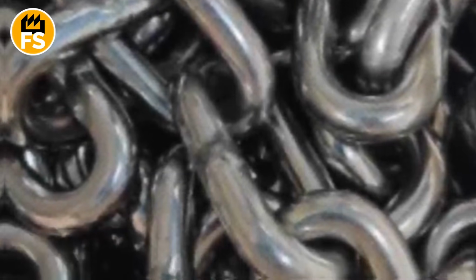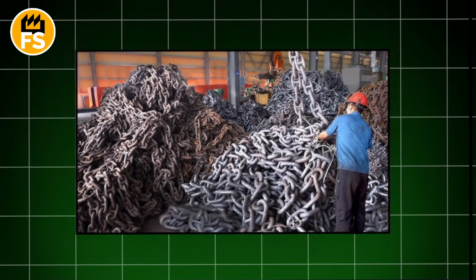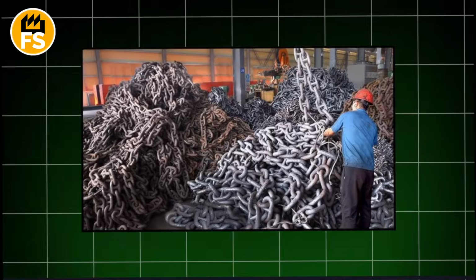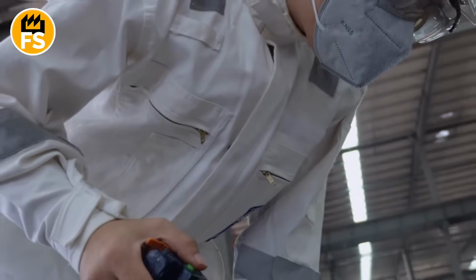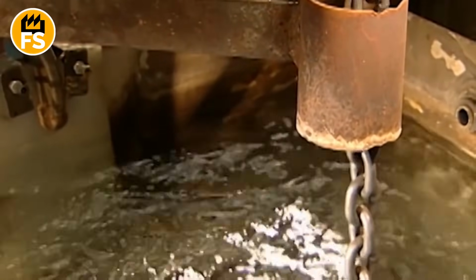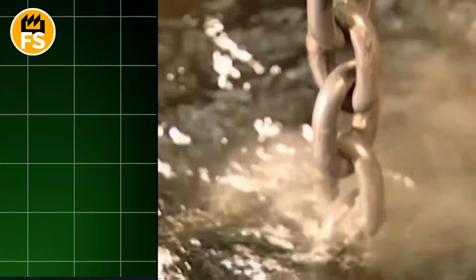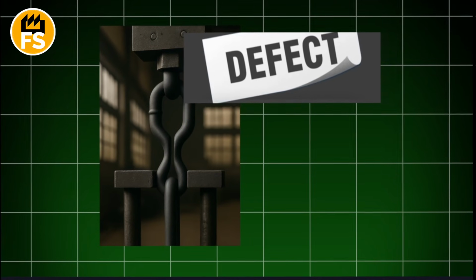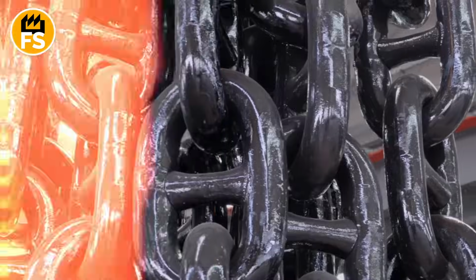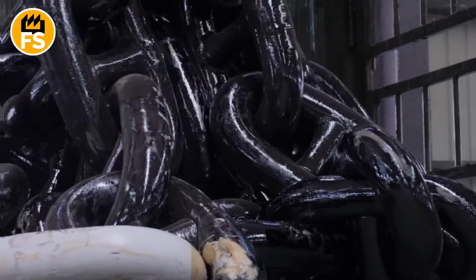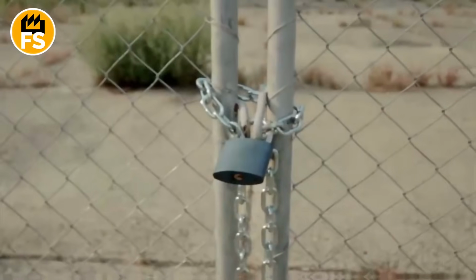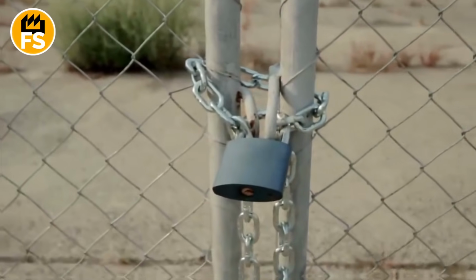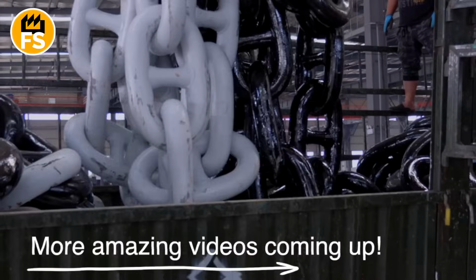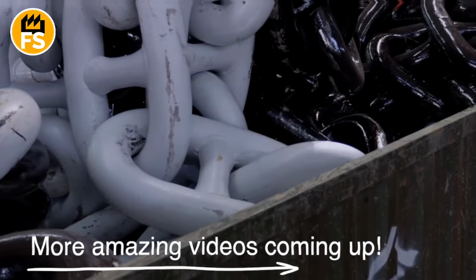In addition to this, other types of control are carried out. Specialists carefully inspect each link for cracks, deformations, quality of welds, and coating. With the help of special calipers and measuring instruments, the compliance of the link sizes, their shape, and the chain pitch with the specified parameters is checked. From each batch of chains, samples are taken, which are then subjected to breaking tests. This allows us to determine the maximum breaking force that the chain can withstand and to make sure that it meets or exceeds the established norms. These are brutal but necessary tests that guarantee that the entire batch of products is reliable.